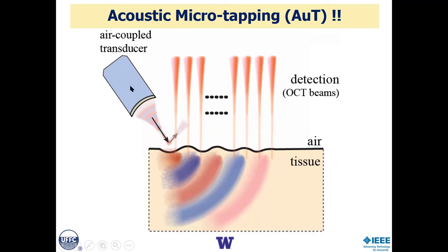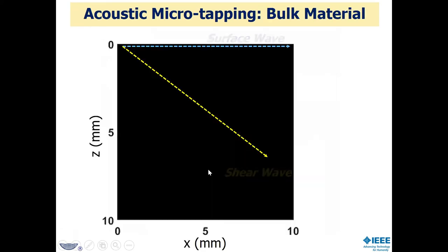So we launch ultrasound through air. Yes, through air. What I will show you are measurements made at 1 megahertz, with a cylindrically focused acoustic lens, which creates a line source. That reflection creates a little tapper, hammering, which we call micro-tapping, because the line source is about 300 microns in width. That efficiently launches broadband mechanical waves, which can propagate into the material, and we can then image with the real-time OCT.